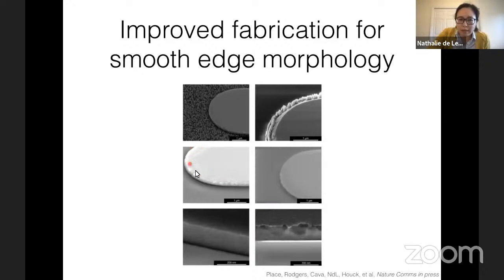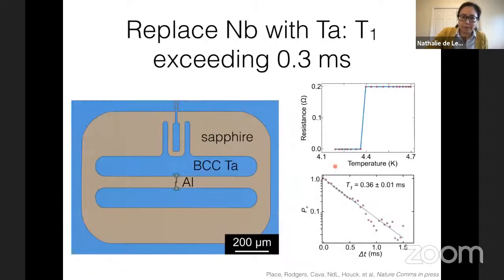Okay, and then finally, after improving the substrate quality and changing the metal, we then had to worry a lot about what our fabrication was actually doing in terms of getting a good edge morphology. Because if you get anything that's sharp or weird looking, it's well known in the field that you get this field concentration in these nanoscale metal structures, which can really enhance your surface participation ratio, which enhances your losses. So we did a lot of fabrication development to be able to get these smooth structures.